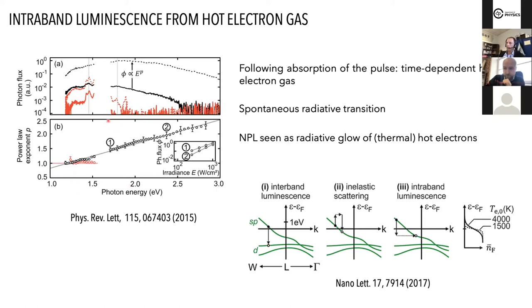We'll be focusing here on the right-hand side of the panel, which is this upconverted photon. So this is at higher energy than the laser. The laser somewhere sits here. So we're looking at the photon energy here up to a little bit short of 3 eV. And what they found is that they have a linear relationship between the power law exponent P and the photon energy. So to specifically answer the previous question, yes, if you integrate the whole spectrum into one detector, then you get a quasi-quadratic dependence. Sometimes it's non-integer. But now if you do a spectrum analysis of this power dependence, you will find that the nonlinearity order scales linearly with the photon energy.